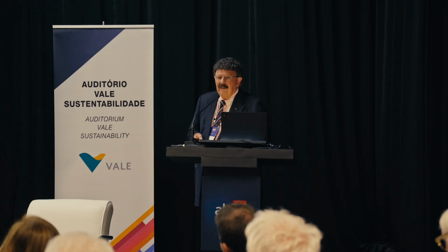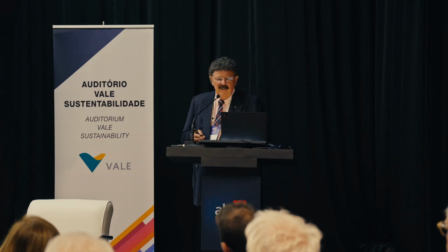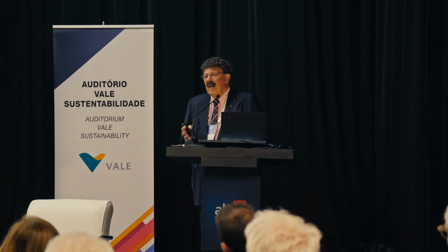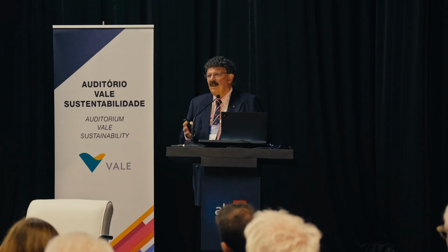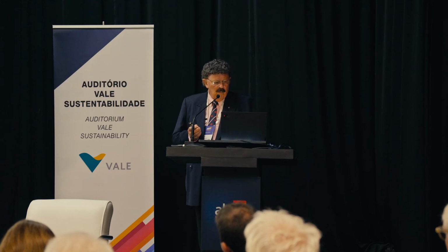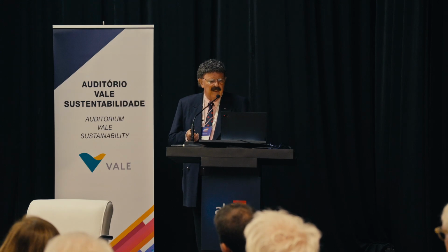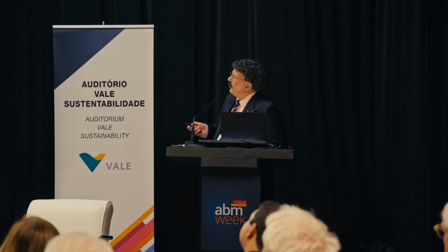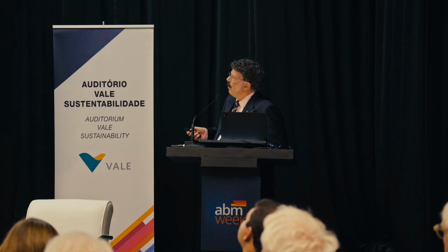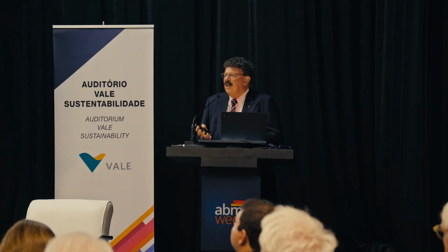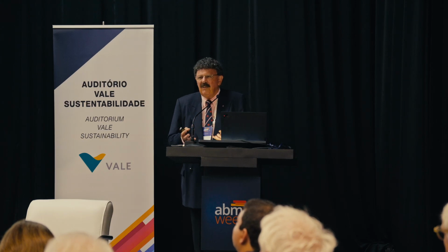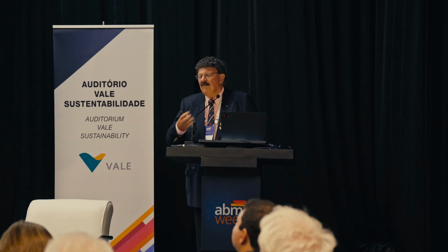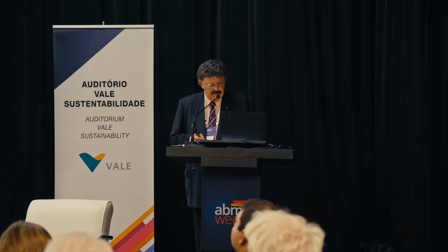This is way below that, half of that. So these alloys, I think, people are looking at them, but they need a lot of things done to them to make them more ductile. Their ductile brittle transition is too high. So what we've done, again, by the way, just quickly, you get oxidation in the boundaries, you form niobium oxides. This is why the grain boundaries are so brittle. So they have a high ductile brittle transition associated with boundary situations and probably with environmental effects in those boundaries.